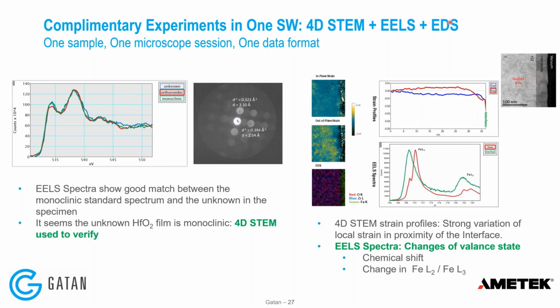But EDS signal, of course, as I showed in one of my first slides, can be collected simultaneously with a 4D STEM data acquisition or as you're collecting your EELS spectrum. So here are two examples. The one on the left, we were looking at the sample and we were not sure about the crystalline structure of the material, and we collected some 4D STEM data to make sense of what we see in the EELS spectra. And the one on the right is looking at the strain at the interface in the sample. By looking at the EELS spectra and the valence state of the material at the interface, we could explain why the strain is changing there.